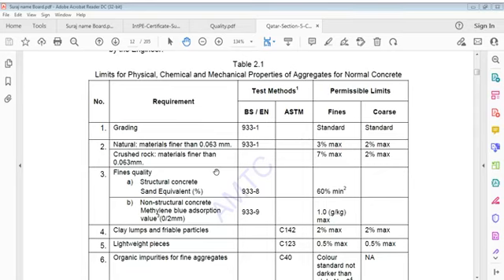This you can say is fines quality. For structural concrete, the sand equivalent is 60%, and for fines in non-structural concrete, the methylene blue adsorption value is 1 gram per kilogram maximum.